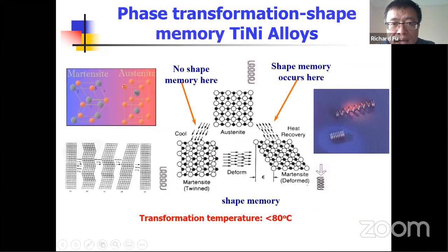So what is the reason behind the shape memory effect? Basically, there are just two phases changing with the temperature. At room temperature, at low temperature, it is martensite, which is a zigzag twinning structure. It's easily deformed. Once you deform it, it becomes deformed martensite. But once you heat it up, it automatically transforms into austenite. Austenite has the same shape as before the deformation.